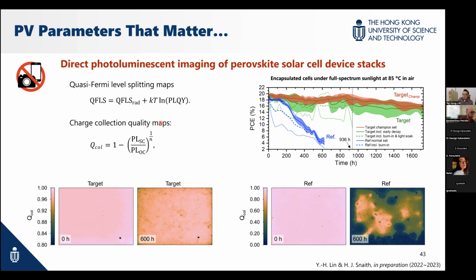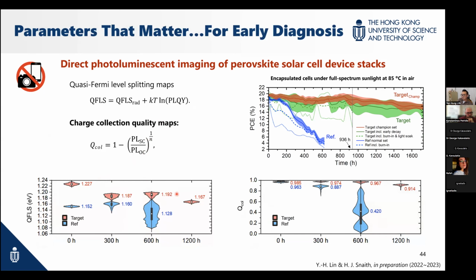It might not be too straightforward to look at just this math, because when we do the comparisons, the quasi-Fermi level splitting doesn't show massive differences, but when we look at the collection qualities, they are very different. So we are trying to identify what kind of physical property we can use to further quantify and better predict this kind of degradation process, especially for early diagnostics.